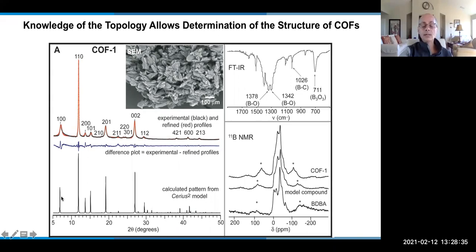And we already had predicted what the X-ray powder diffraction should look like. This is the simulated pattern based on a hexagonal arrangement, and this is the experimental pattern overlaid with the refined pattern. We also do spectroscopy such as IR and NMR to make sure that the right linkages are being formed and to assess the completeness of the reaction.